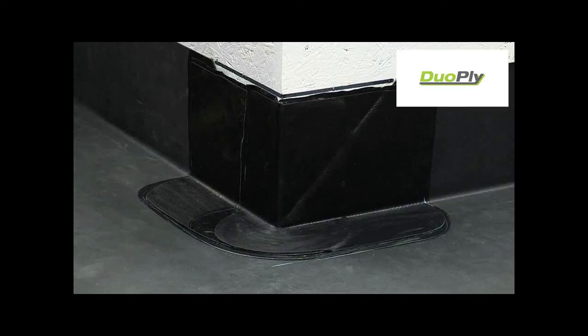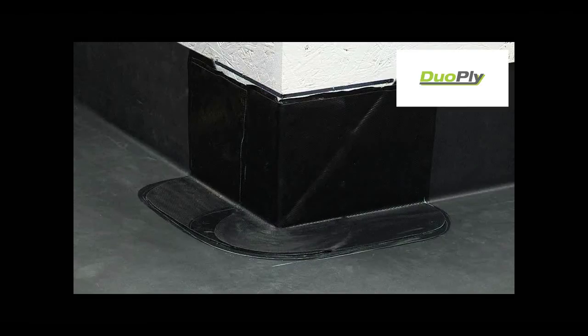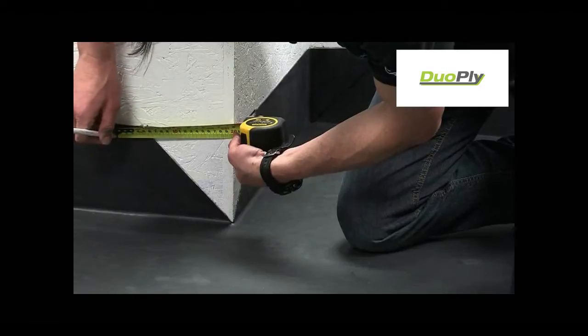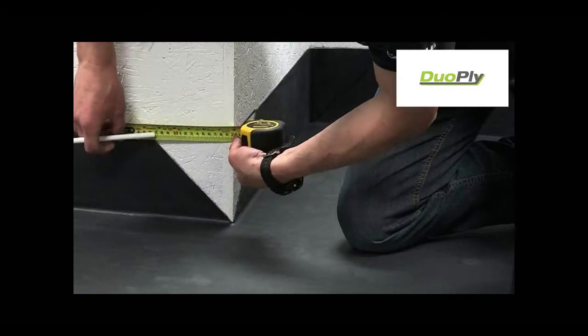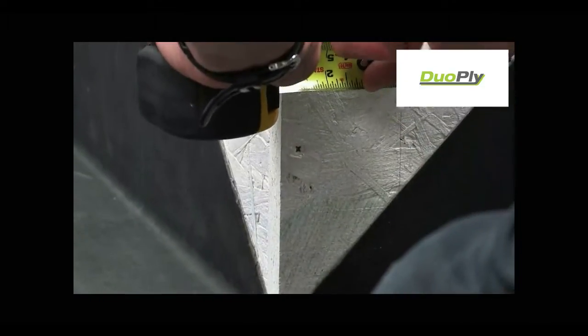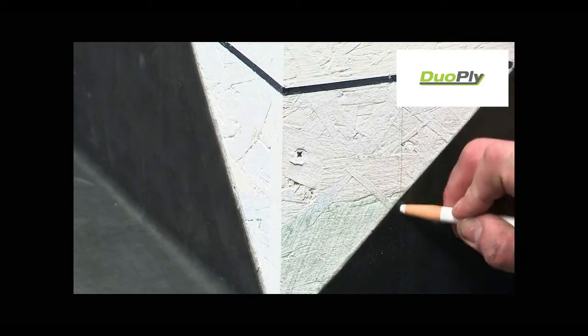Corners can be completed with two pieces of 228 mm pressure-sensitive uncured flashing tape. This reinforces the strength of the detail and makes the tapes easier to handle. Mark out the position of the pressure-sensitive tape. The tape must extend 50 mm beyond the cut membrane at its highest point and 75 mm round the corner.